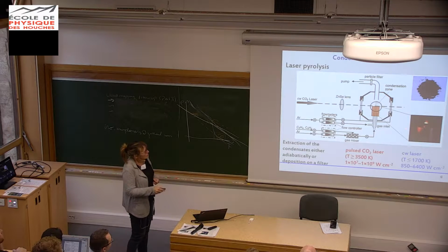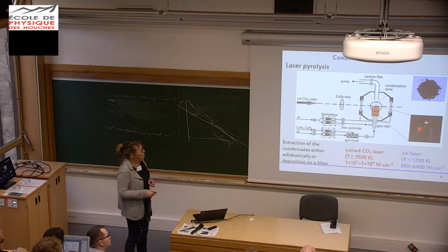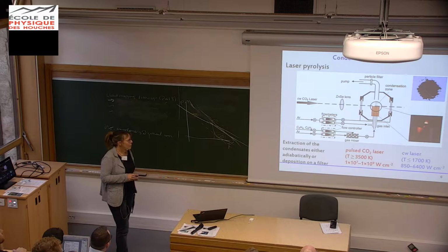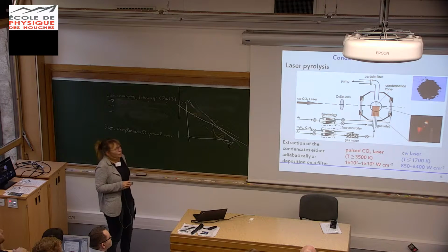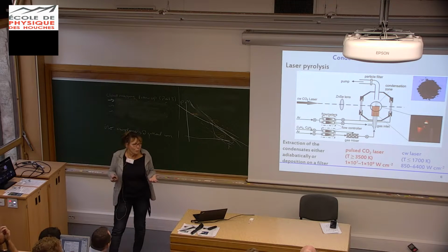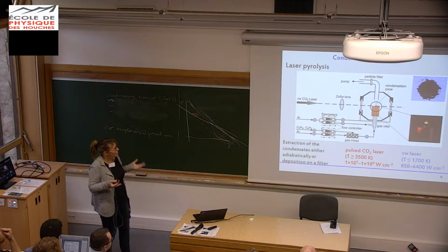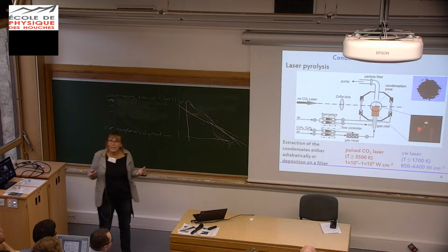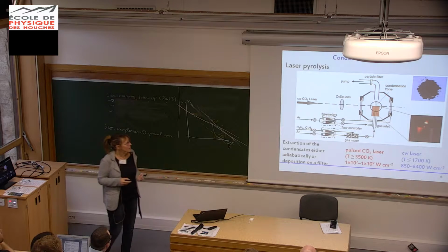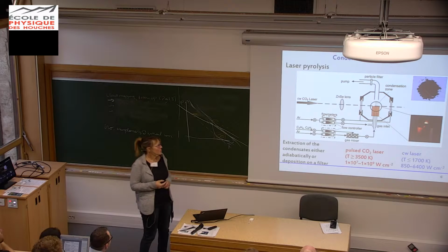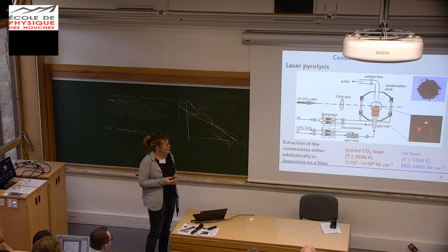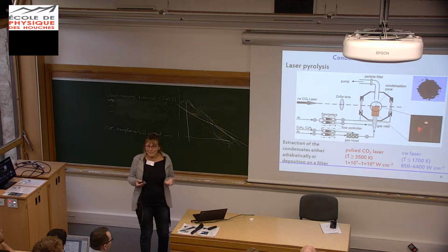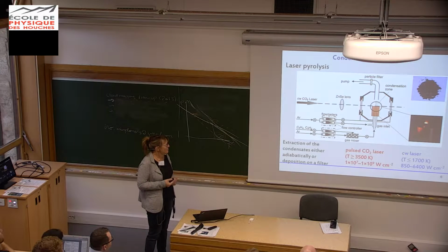The condensation zone looks like this: it's a small flame, and condensation takes place in the cooler part of this flame. This method can be used not only for carbon but also normally for silicates, but the requirement is that you have a gaseous precursor. We have already used it to produce iron silicates, but it's difficult for magnesium because there is no gaseous precursor for magnesium.